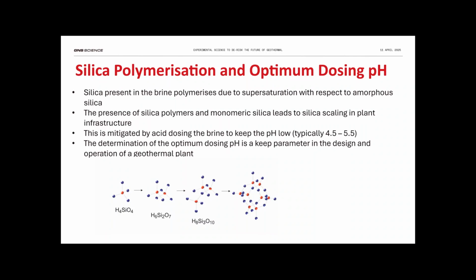Now, the common everyday way of mitigating silica scaling in plant is to acid dose, which is a very effective technique, typically with sulfuric acid, giving a pH between 4.5 and typically 5.5, and that is very effective in the plant for mitigating silica scaling. However, every plant is different, every brine is different. The question is, what is the optimum dosing pH for the plant? And this is an important question because if your plant isn't constructed yet, you can't test it in the plant. So you have to determine ahead of time what dosing equipment you require for your plant. So it's nice to know what the optimum dosing pH is before you actually do the engineering design.